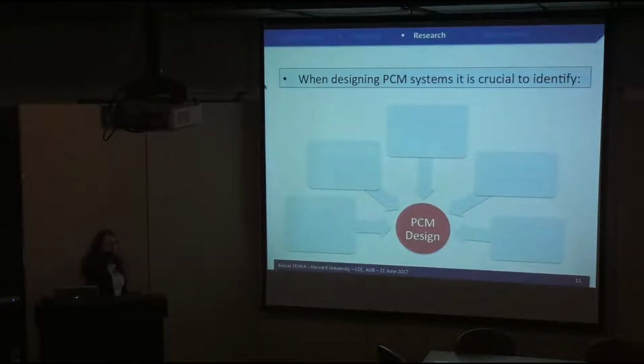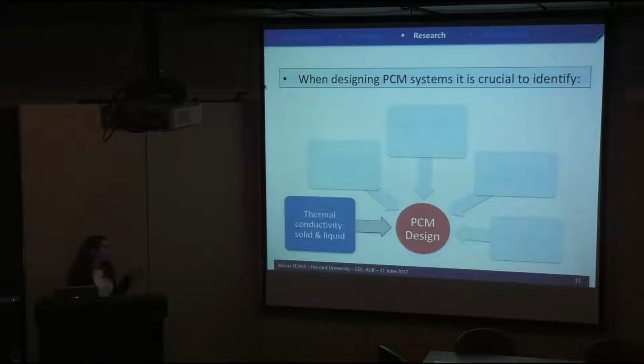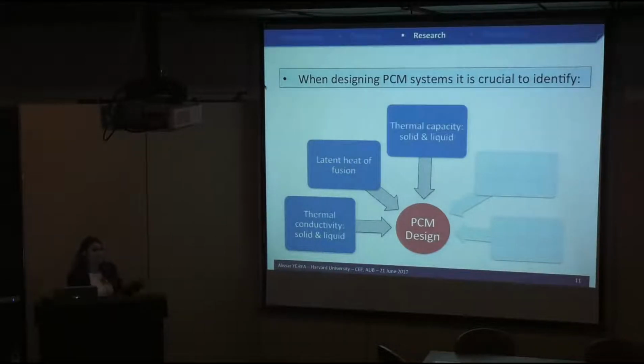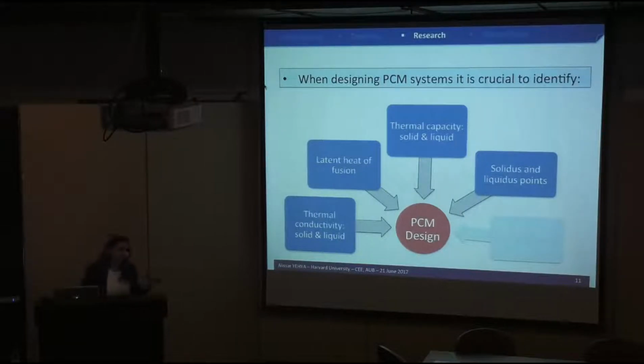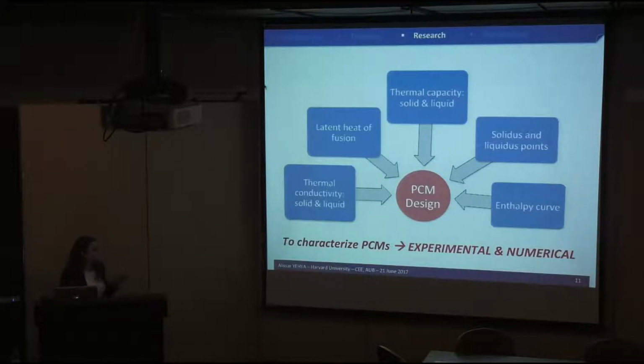When designing a phase change material system, it's crucial to identify the thermophysical properties of phase change materials. First, the thermal conductivity in both solid and liquid phases. Then the latent heat of fusion, also the thermal capacity in both solid and liquid phases, and the onset of melting and onset of solidification, because it's very important to know when the material will solidify or melt in order to predict the fusion times and make them coincide with the daily demand.